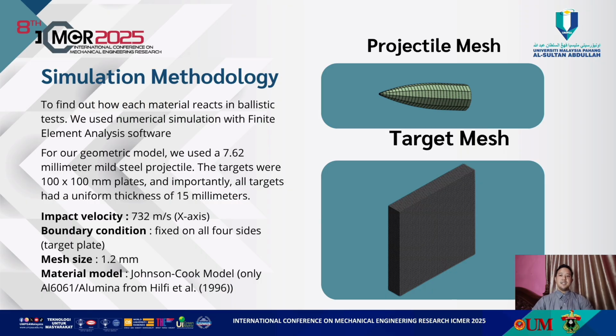For the material models, we used the Johnson-Cook model for the composite, while the data for the other materials were taken from the software library. The parameters for this model were validated using data from the literature from Hilfe and Brar in 1996 for the aluminum 6061 with 15% aluminum oxide.